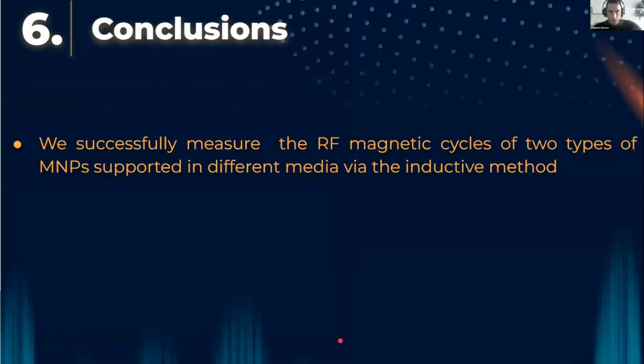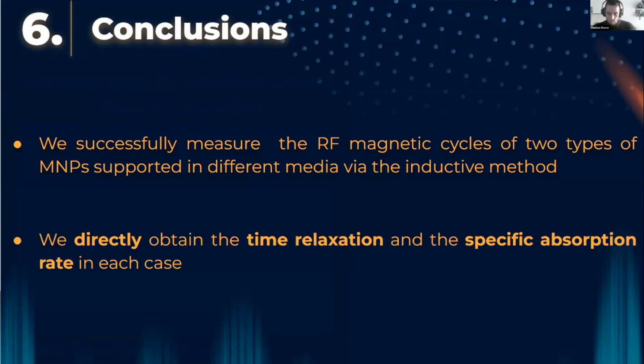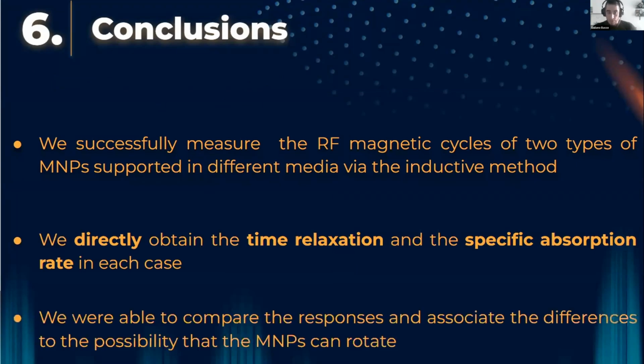So, conclusions, yes, very quickly. In both systems, we were able to directly determine the specific absorption rate and the relaxation time. As far as we know, no other research group has reported measurements of this kind. And due to its simplicity, we envision significant potential in implementing this groundbreaking approach in future experiments.